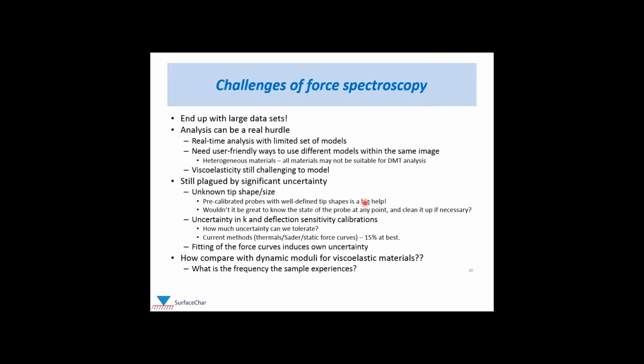But there are still significant challenges in force spectroscopy. First, we end up with large data sets. Second, the analysis can still be a real hurdle. In terms of real-time analysis, it's still done with a very limited set of models. Probably the best way to approach force spectroscopy for quantitative measurements now is you collect the data and then you do your analysis afterwards, where you have more flexibility in terms of the models you use and the algorithms that you can use for different parts of the force curves.